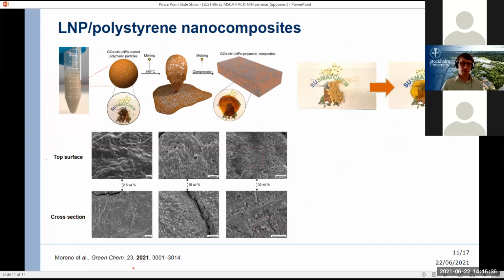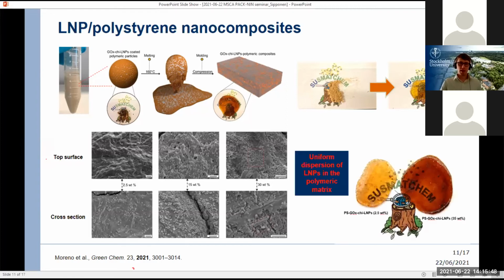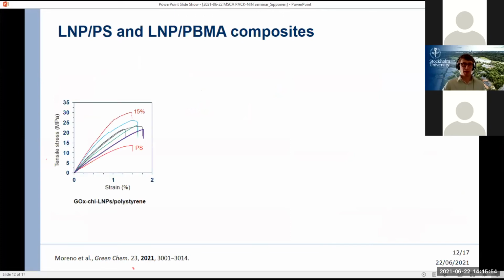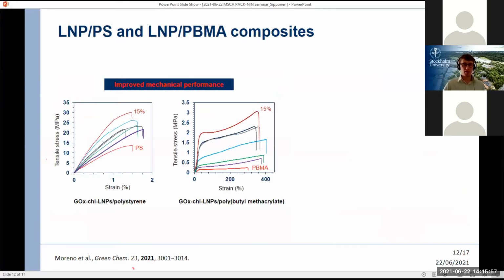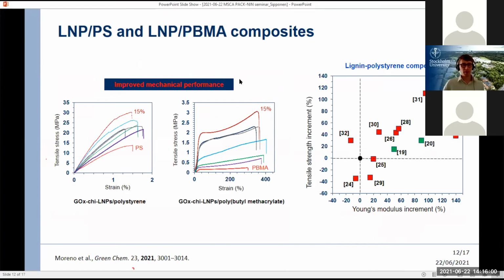Here the key was that even though we were melting this material, there was no clear separation of the phases. So the lignin particles remained very finely dispersed in the matrices. And basically this resulted in an excellent mechanical behavior. I summarize it here. So even in this case, we found that there was a sweet spot at 15 weight percent of the lignin particles in the system, but even with higher amounts up to about 30%, we can still actually exceed the performance of the pure polymer, especially in the case of the PBMA.